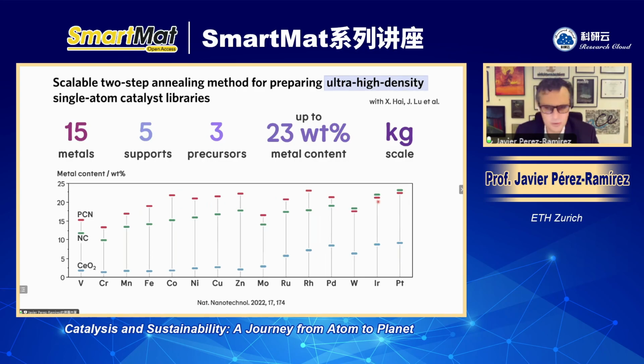Rhodium or platinum or 20% iridium, you can see. Carbon-based carriers have many more coordination sites, so they can accommodate much larger metal contents compared to inorganic carriers. Inorganic carriers like ceria at best could accommodate a significant amount of, let's say, palladium, I think is this one here, about 8 or 9 weight percent. But if you move to carbon-based materials, you can see that systematically you increase the loading because of the availability of coordination sites. It's much easier to make them.